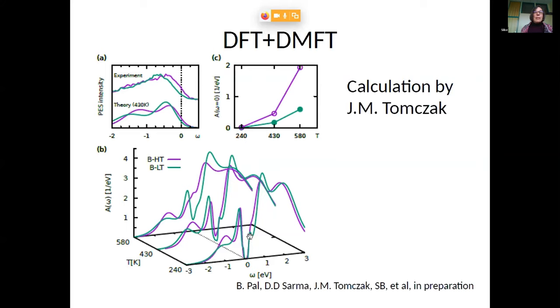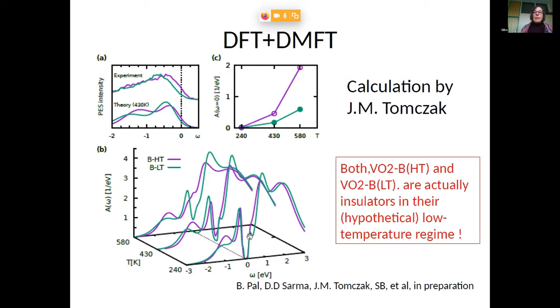And that is what I alluded to before, the extreme sensitivity of the electronic properties to temperature, which is carried here by the many-body self-energy. So we are hypothesizing that both high temperature and low temperature B phases are in principle insulators if you were able to look at both of them in their low temperature regime. Now this is of course intriguing. So what is really happening in terms of temperature dependence and what is causing these changes?